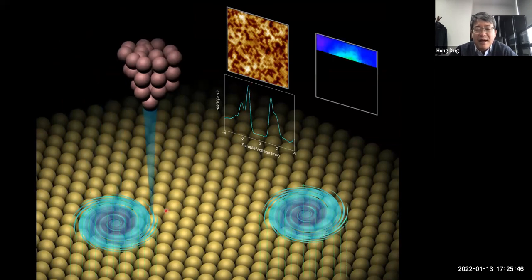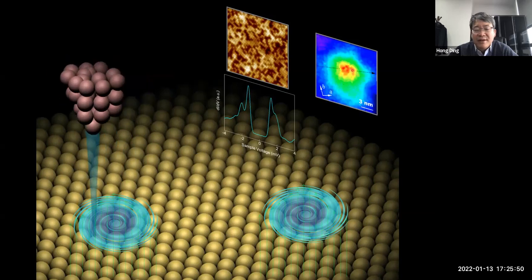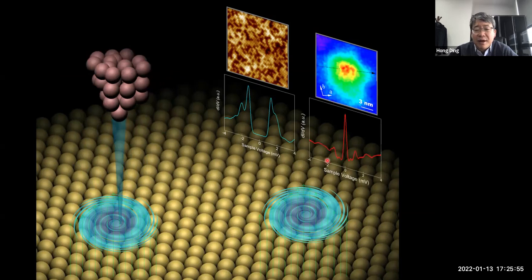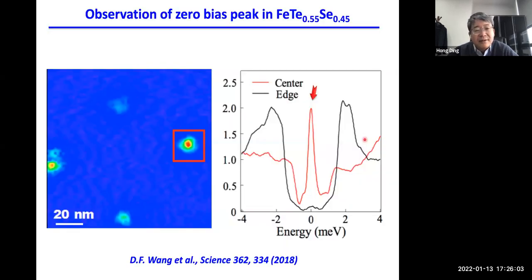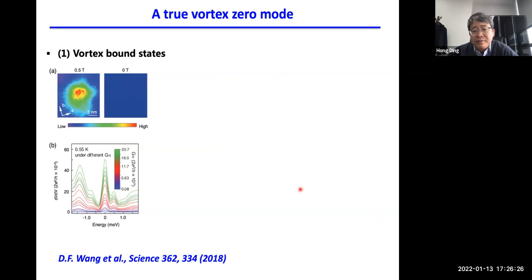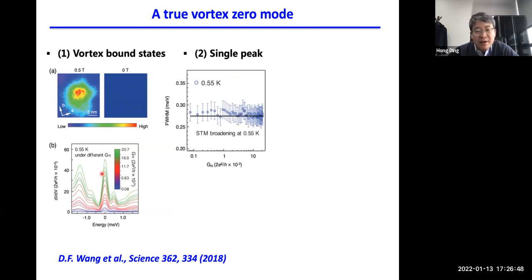If we apply a magnetic field, we see the vortex, and here is the vortex image. And if we do dI/dV in the middle of the vortex, we actually see in the middle of the superconducting gap a very robust zero mode. Here I show it again, the zero bias peak in this material. Outside, the black curve shows the hard gap, and then inside in the middle we have this zero mode, which is quite strong. And this is a true vortex zero mode. First of all, without magnetic field, we don't have anything. So it's not an impurity state. And we can also change the coupling between the tip and the surface, and the single peak stays on with essentially the same width, controlled by our resolution.